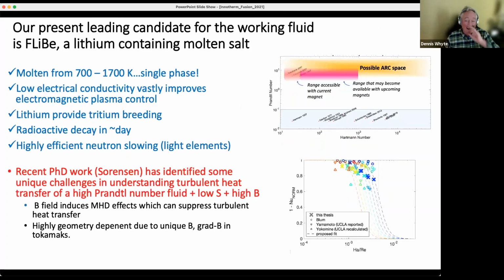Our present leading candidate for this working fluid is FLiBe, which you're probably not familiar with. This is a fluorine lithium beryllium salt, a lithium-containing molten salt. The reason we use it is that it's molten from 700 to 1700 Kelvin. It's all single-phase flow, which is spectacular. Of course, the high temperature really helps the overall economic mission for fusion, with higher Carnot efficiency. It has low electrical conductivity, which vastly improves electromagnetic plasma control because there's much less material to go through electromagnetically. It has lithium, which provides the tritium breeding, and it radioactively decays to safe handling within a day or two. So it really is very attractive, and it's highly efficient at slowing down the neutrons.